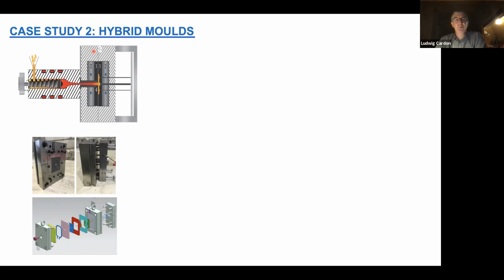But once you want to produce short production runs, a possibility is to replace the inserts, the core and cavity you use inside your mold, by other types of materials. I will show you some results on that immediately. Some of them that we applied were, for instance, an aluminum mold, a titanium mold insert, or even 3D printed plastic molds. So we develop plastic inserts and incorporate them here. One is our mold frame, two is our cooling system, and three is, in this case, our 3D printed polyamide 11 mold.